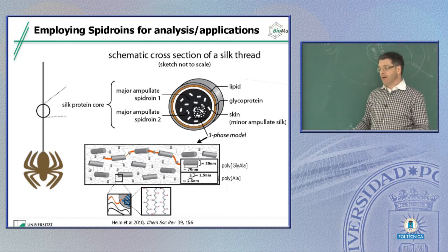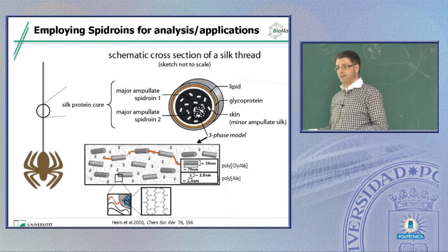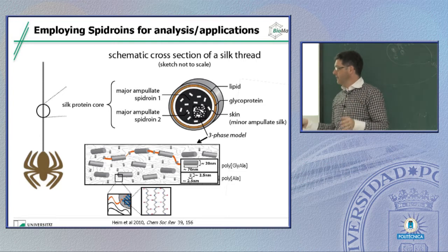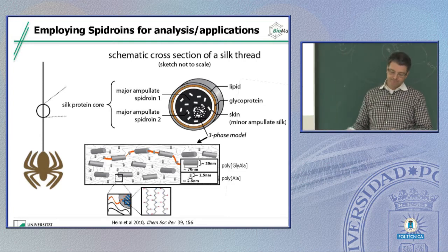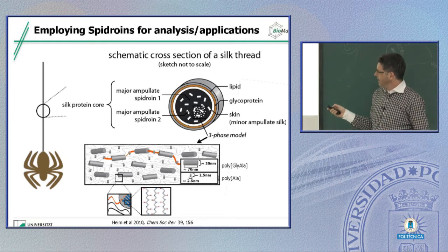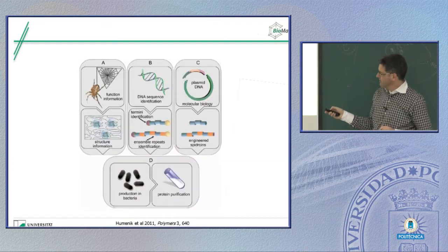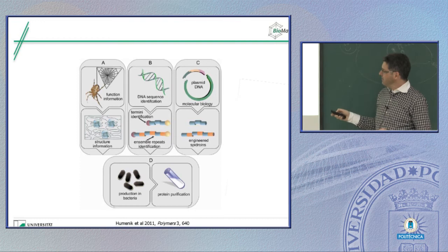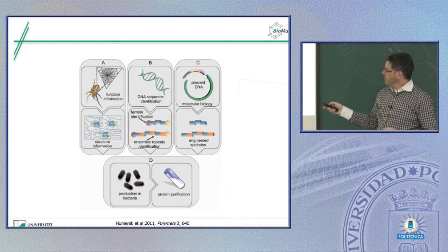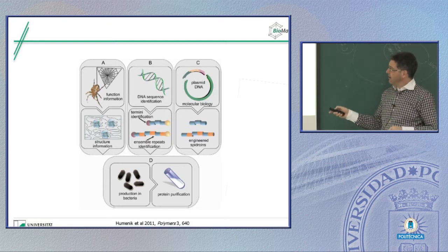And this has not just been done by us. There are many, many people doing research on that, and they started in the 1950s with X-ray diffraction studies and so on. And there's quite a large database on the structure-function relationship. It's pretty clear that these small crystals are based on polyalanine sequences. So the crystal sizes are roughly between 2 and 3 nanometers in all dimensions. The larger crystals are typically formed by glycine-alanine runs that are then repeated over time, and there we have crystals of like 20 by 70 nanometers.